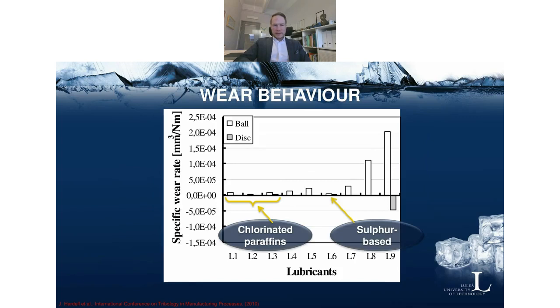In terms of specific wear rates, and this is now the ball sample versus the disc sample. So the bars in white are the stainless steel ball, and the gray bars are the discs. So obviously the ball wears more than the disc, not very surprisingly. But what you can notice here is that you have a very low wear rate of both interacting surfaces when you use the chlorinated paraffins, and that is the whole point of using those kind of lubricants. The sulfur-based chemistries did not really perform that well, except for one, as you can see, L6, that gave very low wear on both of the samples.